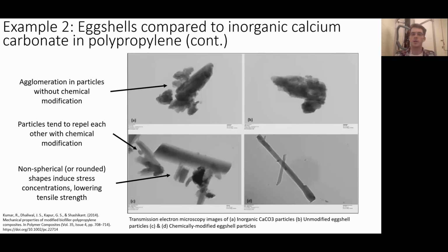So in order to back this up, the authors took transmission electron microscopy images of the 3 different kinds of particles. Images A and B here are the unmodified calcium carbonate and eggshell particles. And we can see there's pretty significant particle agglomeration in those 2 images, again, which will show itself as a decrease in tensile strength and a decrease in tensile modulus as well.